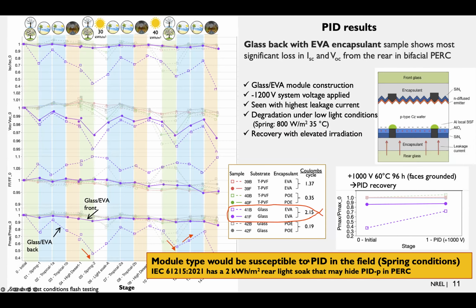So just to look at the data again, to hit that point and make it go home, we saw an important amount of degradation in this spring cycle here, and then recovery under light soak to some extent, and again degradation under spring and recovery under higher temperature and higher light. So again, this module type would be susceptible to PID in the field based on our results in the spring conditions.